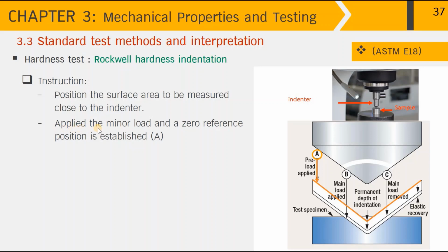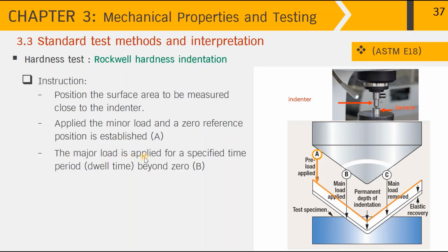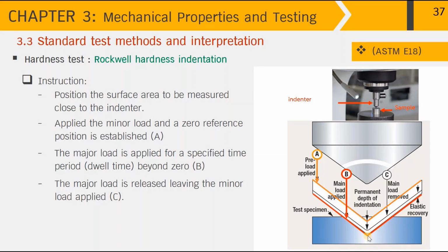To do the test, we have to first apply the minor load, as you can see from a position here. And this is to locate the location that we would like to do the test by applying a very small level of load over here. There's very small indentation taking place over here. After that, we set this level as a 0 reference to position at A. And then the major load is applied for a specified time period, or the dwell time. Then we arrive at B, which is the penetration depth by applying the major load.